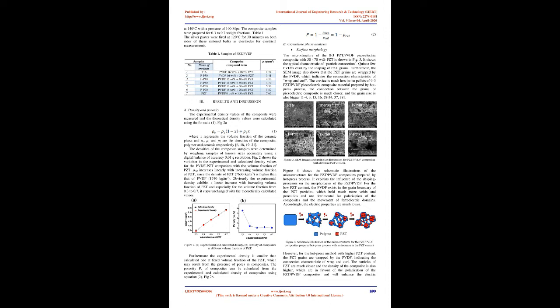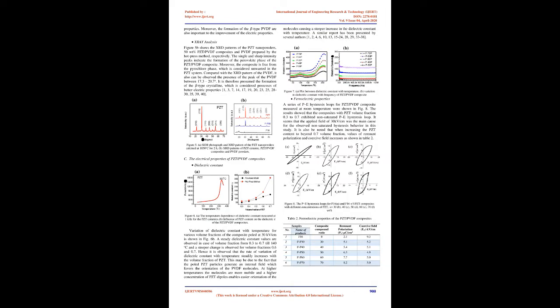The calculated density increases linearly with increasing volume fraction of PZT, since the density of PZT, 7630 kg/m3, is higher than that of PVDF, 1740 kg/m3. Obviously the experimental density exhibits a linear increase with increasing volume fraction of PZT, and especially for the volume fraction from 0.3 to 0.7, it stays close to the theoretically calculated values.